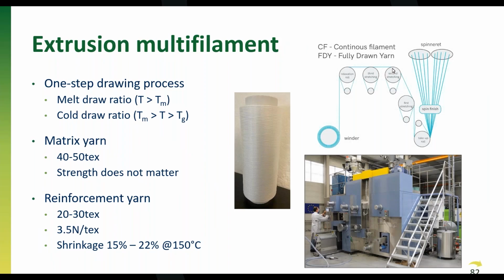Here a little bit finer yarns because this improves the strength and also the distribution within the composite formation. So 20 to 30 tex is the thickness of one bundle, and the strengths we can achieve are 3.5 Newton per tex, so quite similar to the bicomponent yarn, but we have a shrinkage of 15 to 22% at 150 degrees, which is very high. It's very high because this is also quite close to the melting temperature of the reinforcement yarn. So the grades that we've been using melt around 175 degrees Celsius. So that's only 25 degrees lower, or the melting point is 25 degrees higher than the processing temperature at around that 150 degrees.